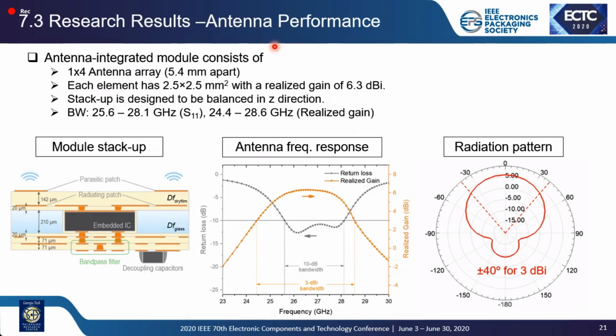And this is the antenna performance. The antenna consists of a 1x4 antenna array, and they are 5.4 millimeters apart, and each element is 2.5 by 2.5 millimeters squared, with a realized gain of 6.3 dBi, as you can see over here, as a function of frequency. And the stack-up is balanced on both sides of the glass substrate. And if you look at the bandwidth, which is pretty wide, it has more than 4 gigahertz. The realized gain is higher than 3 dBi, and also we got pretty good realized gain over ±40 degrees.